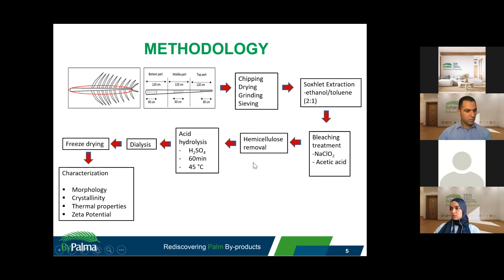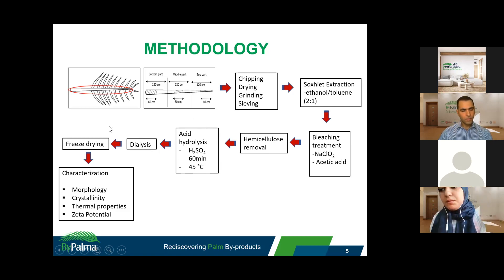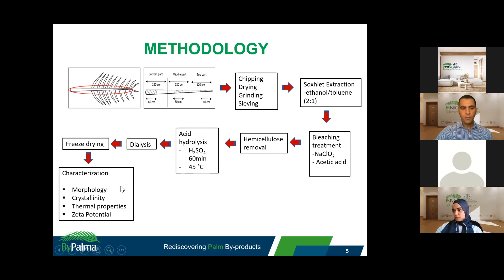The bleached samples were then subjected to hemicellulose removal using 6% potassium hydroxide for 24 hours. Once the hemicellulose was removed, the most important part was acid hydrolysis using sulfuric acid for 60 minutes at 45 degrees Celsius. After hydrolysis, the sample was neutralized using a dialysis tube. Once it reached pH around 5 to 6, the sample was freeze-dried before further characterization. The characterization covered morphology, crystallinity, thermal properties, and zeta potential analysis.